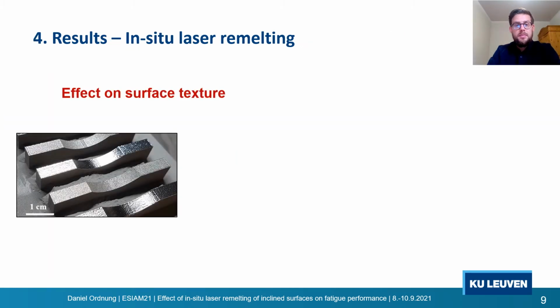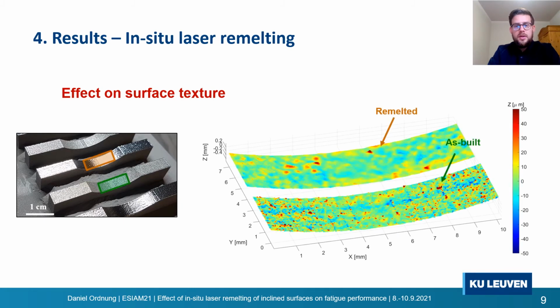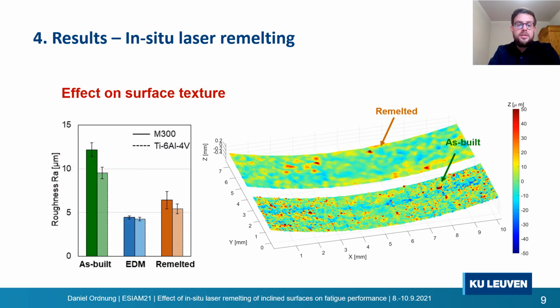Results of laser remelting. First of all, the laser remelting process has a very visual and clear effect on the surface texture. When we look at a 3D surface measurement, we can see that the remelted samples show a very smoothened surface compared to the as-built. And this is actually confirmed when we look at the surface roughness values. For maraging steel, the surface roughness was reduced by about 47%, and for titanium it was reduced by about 43%.